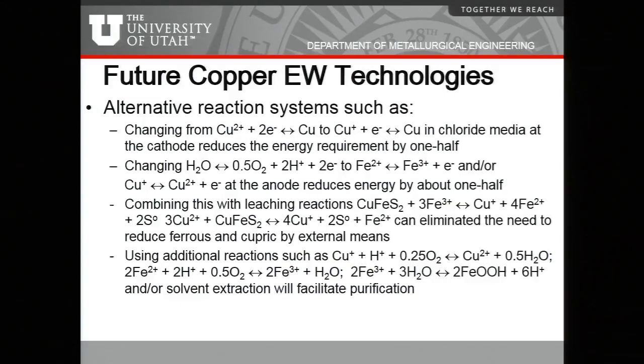And when that's combined, now there is a problem with parasitic reactions, and so there has to be some things that are done with flow or potentially with diaphragms to make sure that you don't have too much of that crossover. But I think you can manage it pretty well and actually couple it in with leaching by providing an oxidant for leaching while simultaneously providing the reduction for the copper reaction. And then, of course, if we do that kind of a leaching scenario, we have to deal with some of the other entities, the buildup of iron, and there's some reactions out there that people have investigated to handle that.